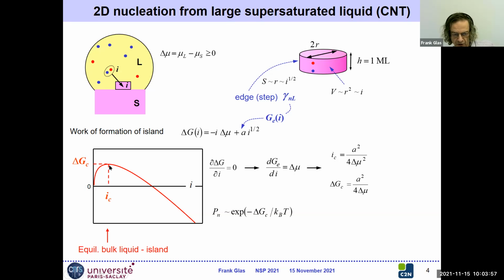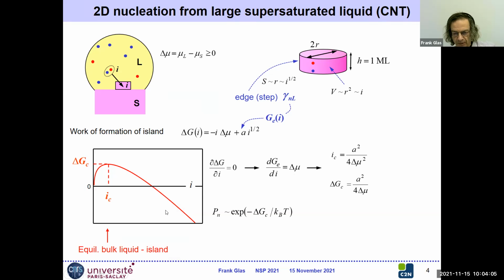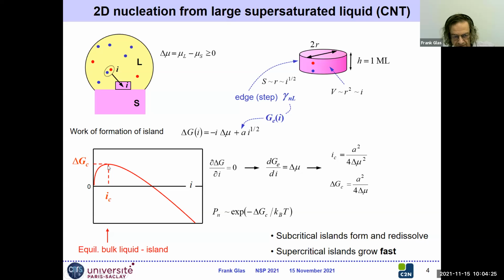And it's an unstable equilibrium because if I add more pairs, then I will continuously decrease the energy of the system. Now, this barrier scales as the square of the edge energy divided by the chemical potential, and the nucleation probability is thermally activated with this energy barrier. Now, subcritical islands form and redissolve, but if an island has by chance reached this critical size, then we expect this supercritical island to grow fast because any atom will decrease the energy of the system.